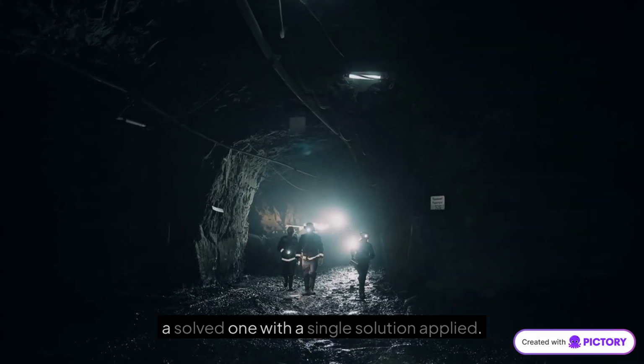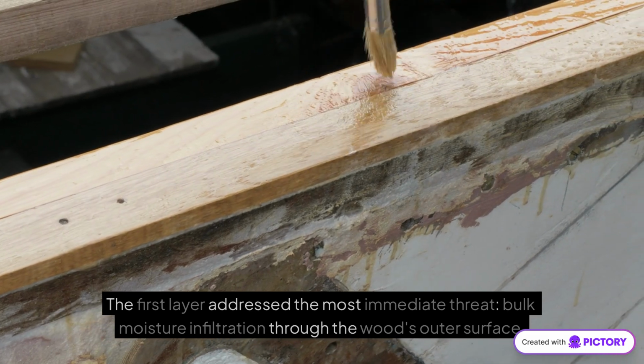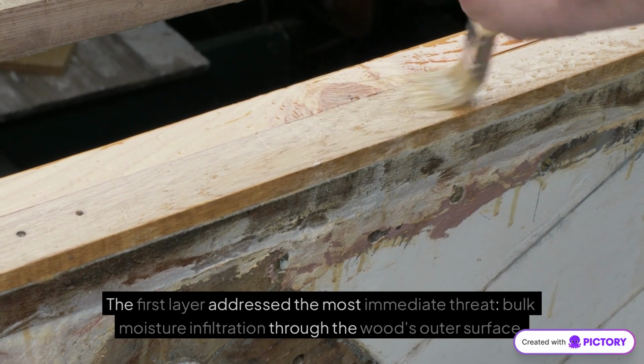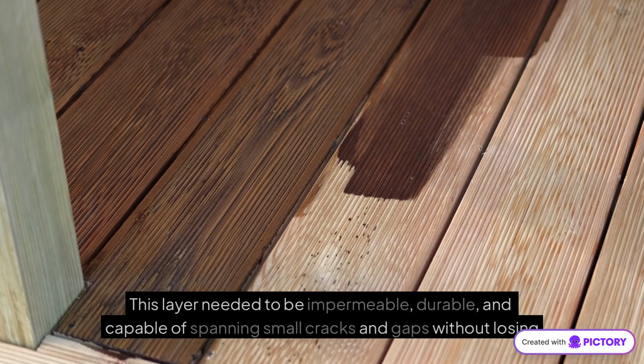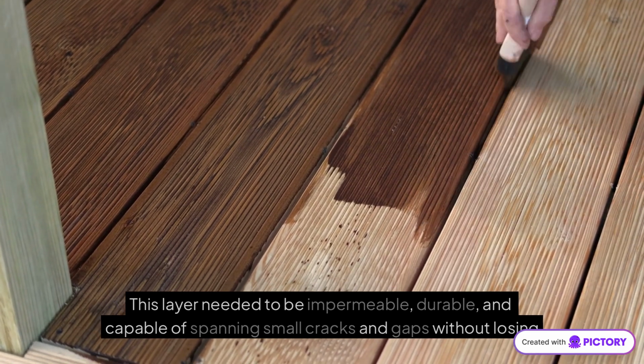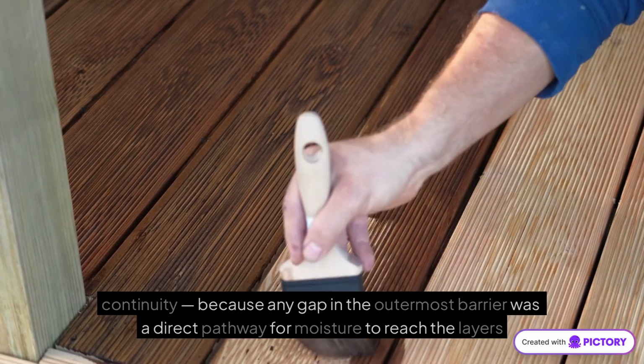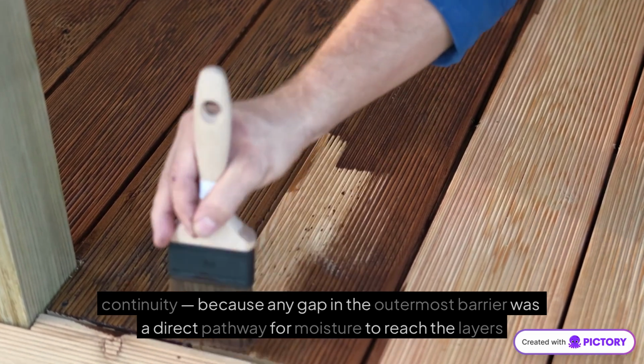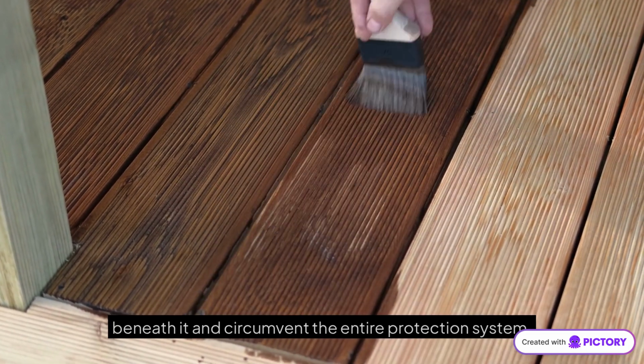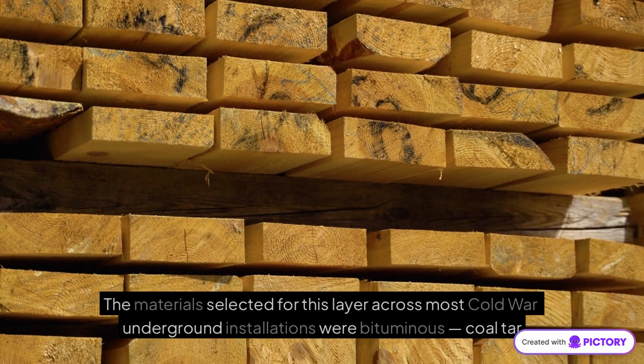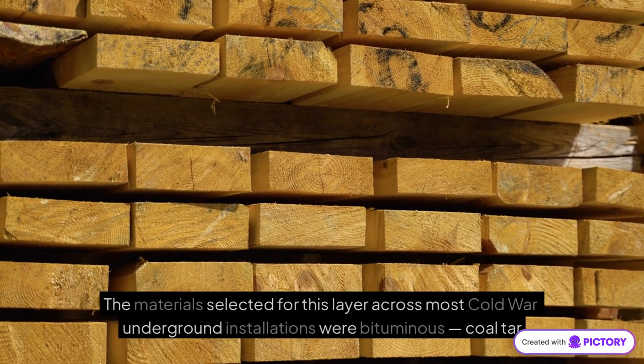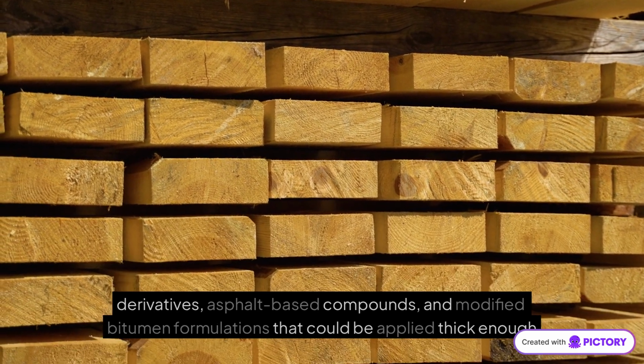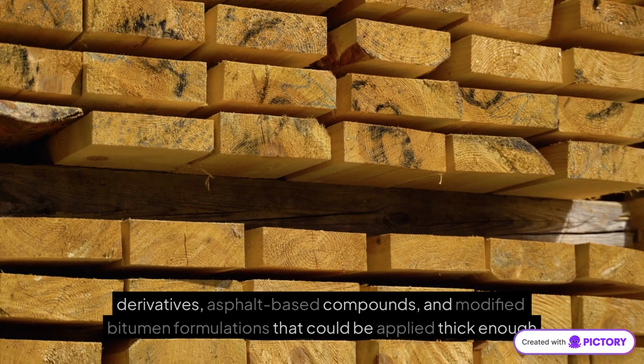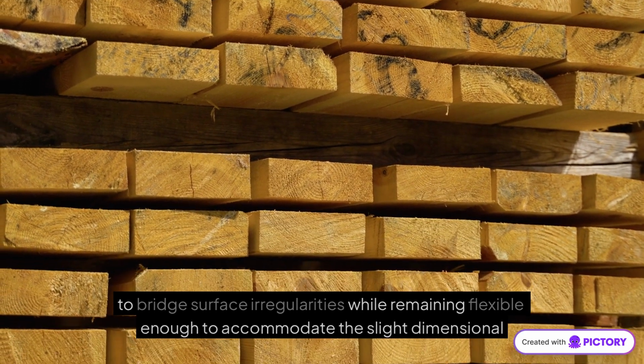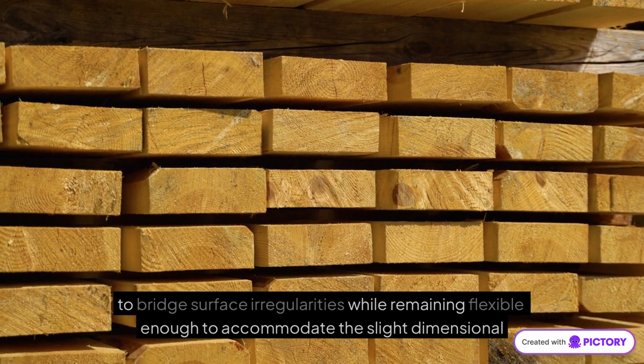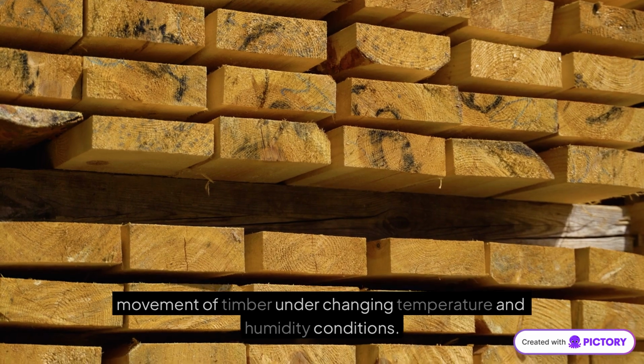The first layer addressed the most immediate threat: bulk moisture infiltration through the wood's outer surface. This layer needed to be impermeable, durable, and capable of spanning small cracks and gaps without losing continuity, because any gap in the outermost barrier was a direct pathway for moisture to reach the layers beneath it and circumvent the entire protection system. The materials selected for this layer across most Cold War underground installations were bituminous, coal tar derivatives, asphalt-based compounds, and modified bitumen formulations that could be applied thick enough to bridge surface irregularities while remaining flexible enough to accommodate the slight dimensional movement of timber under changing temperature and humidity conditions.